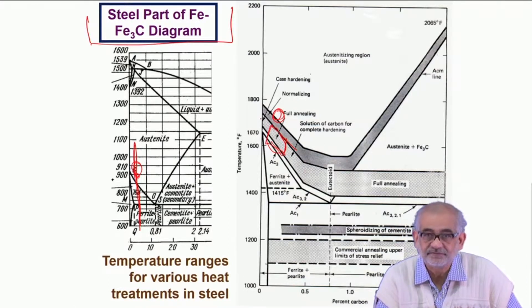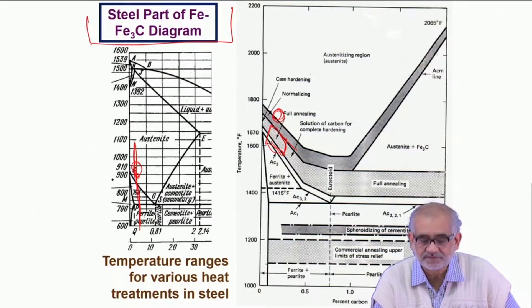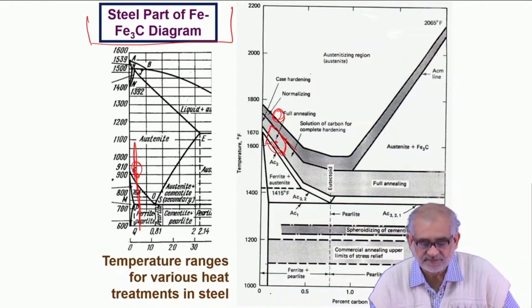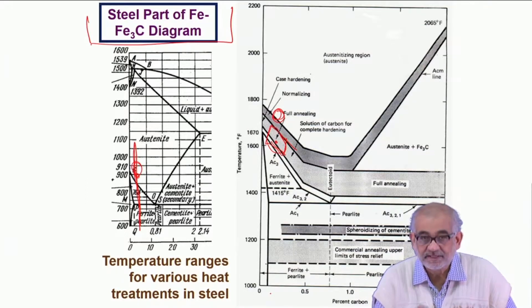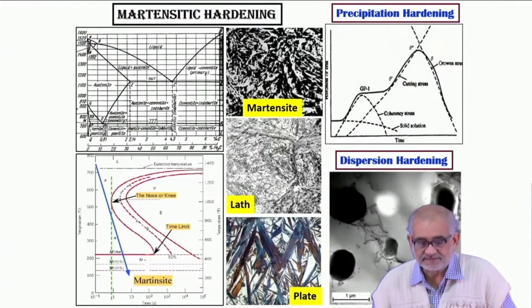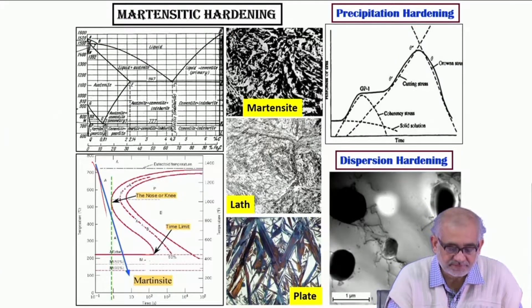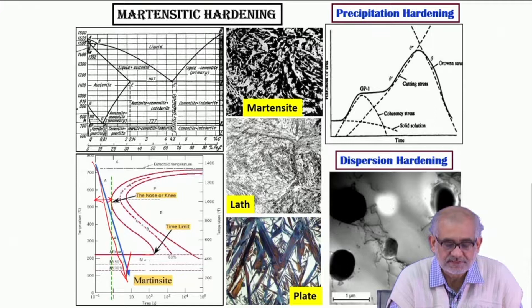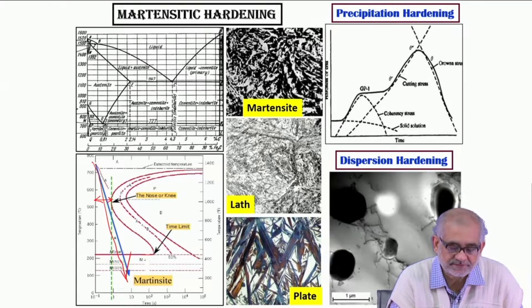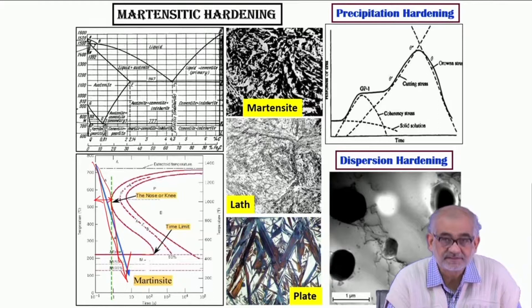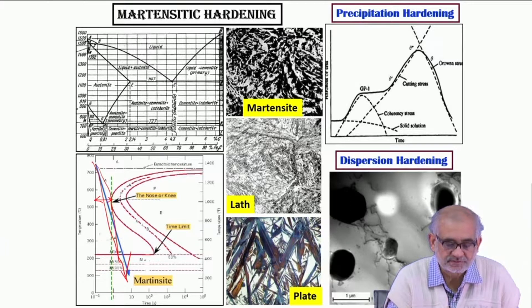So we generally end up getting a very coarse microstructure, and that is not very good - it is actually detrimental for mechanical properties. So when we reheat, we reheat to about this temperature and from there we have to quench fast. Regarding quenching, we are aiming for a quenching rate which will avoid the nose - the so-called critical cooling rate, which is the minimum cooling rate that can avoid intersecting the pearlitic or bainitic start line.